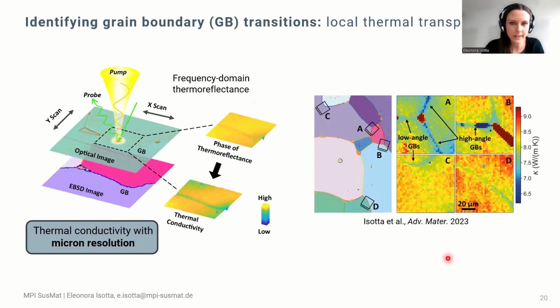In this respect, we have been doing a little bit of work by using frequency domain thermoreflectance to achieve images of thermal conductivity with micron scale resolution. And if the grain size is significantly high, this allows us to measure one grain boundary at a time.